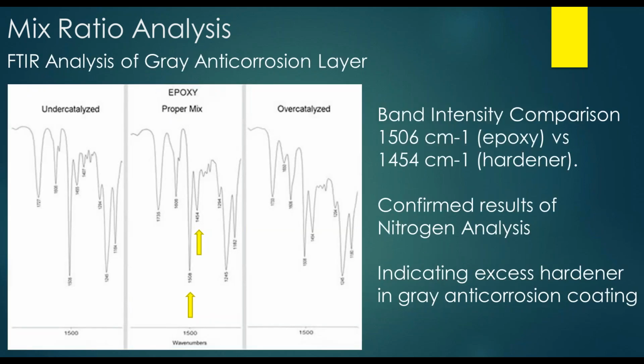These results were confirmed using infrared spectroscopy analysis. In this method, we looked at different peaks in the infrared spectrum of a coating chip that would be attributable to either the hardener or the resin components. The peak that we see at 1506 wave number was attributed to the epoxy component, while the peak at 1454 wave number is attributable to hardener. By comparison of the undercatalyzed versus overcatalyzed images that we show here, you can see that the relative band intensity changes as the mix ratio changes. This analysis indicated the presence of excess hardener in the gray anti-corrosion coating.